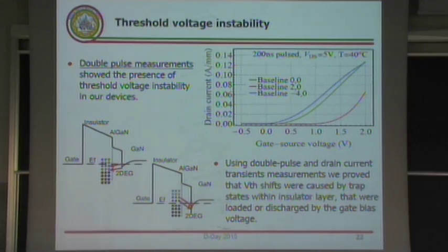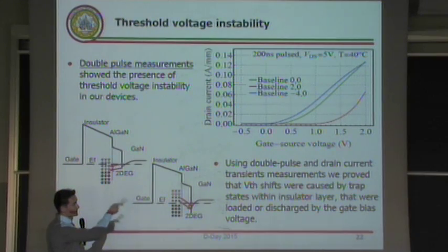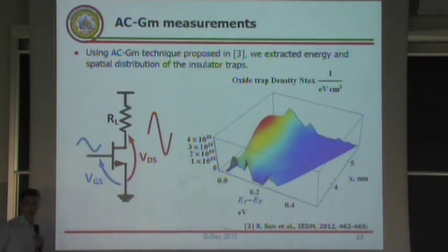So we did a characterization, we developed this model that explained all the experimental data and the threshold voltage shift that we observed. And also we implemented another technique called AC transconductance measurement that allowed us to extract the distribution of trap states within the insulator layer. So basically we extract the energy distribution and also the spatial distribution within the insulator layer.